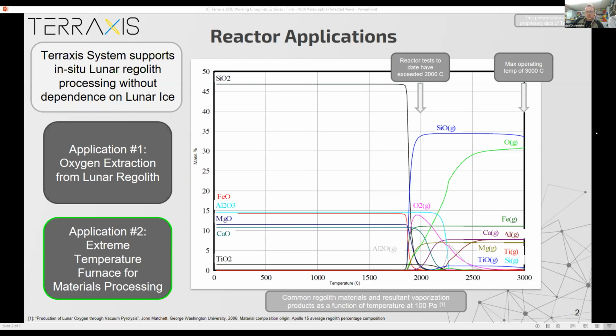So this chart here shows, at a pressure of 100 pascals, what component metal oxides present within regolith disassociate as you increase temperature. One of the big advantages of this process is it's a very high temperature process. So we actually operate in the above 2000 C regime, unlike some of the other processes that use different techniques that operate at much lower temperatures. It's kind of a brute force approach where once you get above certain critical temperatures, you begin to evolve all these different products. So you can see the chart here.